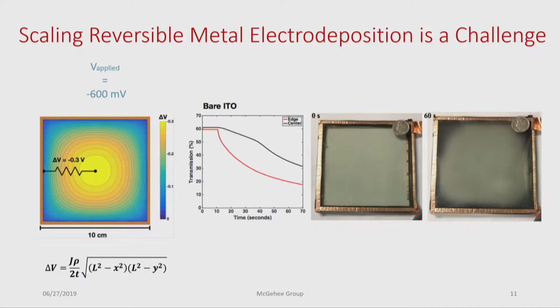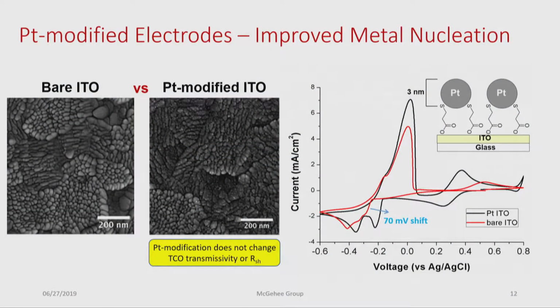So in our group, we had to think, how can we improve the metal nucleation qualities of this TCO? And the way that we went about modifying these electrodes is with platinum nanoparticles. These nanoparticles are about 3 nanometers in diameter, and they're adhered to the surface through a self-assembled monolayer of thiol molecules. If you take a look at the SEM images here on the left, we have our bare ITO surface, and you can see all the grains throughout the TCO. And if you take a look at our platinum-modified ITO, you can see these little white dots just decorating the surface. These are our platinum nanoparticles.